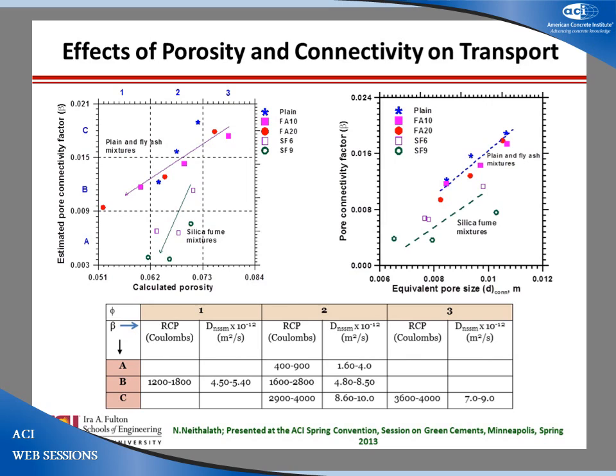So here is some data on conventional concretes, trying to look at what influences transport more. Here is porosity and pore connectivity. You can have silica fume mixes within the same range of porosity, but with silica fume you can have extremely low pore connectivity. For plain and fly ash mixes, the porosity range is quite wide and pore connectivity doesn't drop that much. All these are data from electrical impedance measurements that we've done over time. And again, you can see the pore connectivity with equivalent pore sizes for silica fume and fly ash mixes.